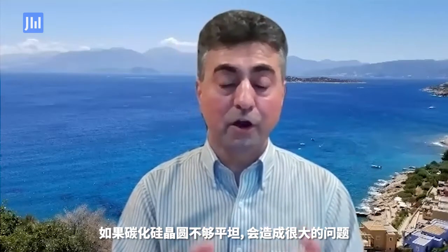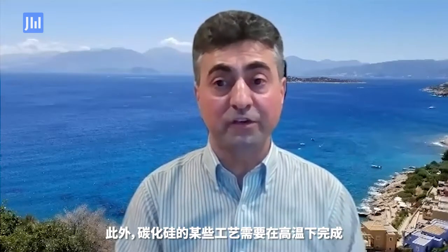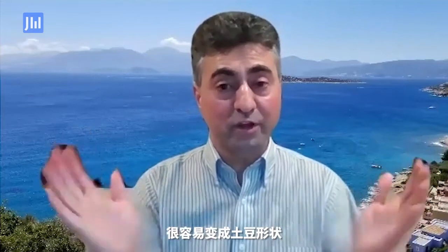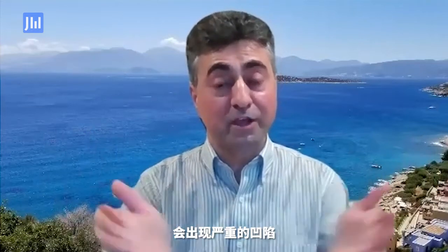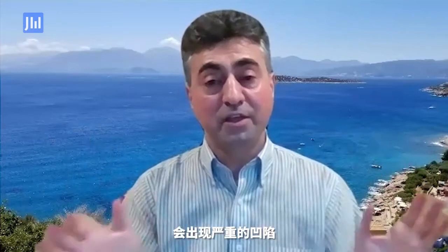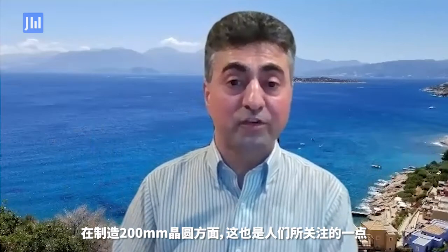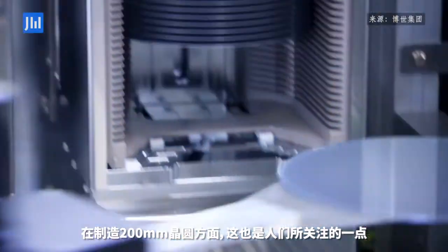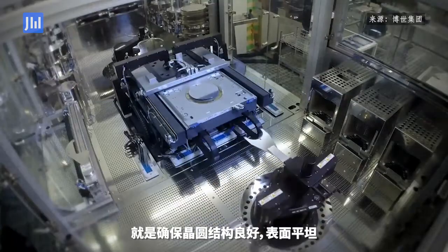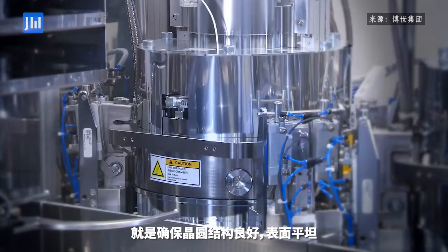And then silicon carbide has some high temperature processes, particularly when you do the implantation anneal, which is typically done at 1600 to maybe 1800 degrees. And at that point, if you start with a wafer that's not very planar, and you go to those high temperatures, your wafer can actually really turn into a potato chip. I mean, it can warp pretty badly, and then it will no longer be able to go through your stepper. So when you get to the 200mm wafers, that's part of what people are looking at: make sure you have a structurally good wafer with good planarity.